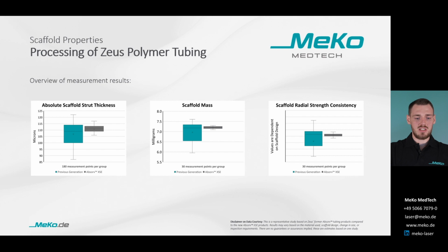Each of the test results shows significant improvements and demonstrates the benefit for the device. Special attention should be paid to the results of the scaffold radial strength consistency. This demonstrates very well that if great material uniformity and very high precision laser cutting come together, bioresorbable scaffolds with much more predictable performance will be the outcome.